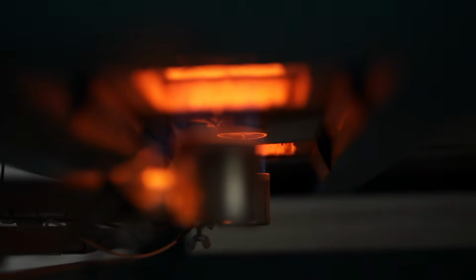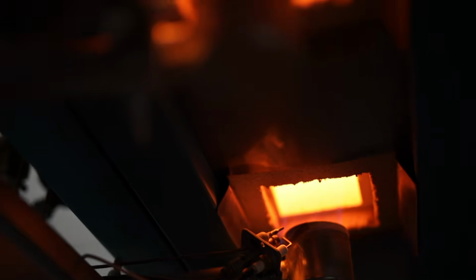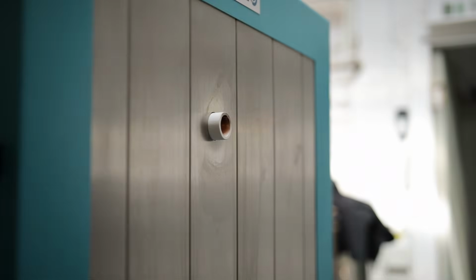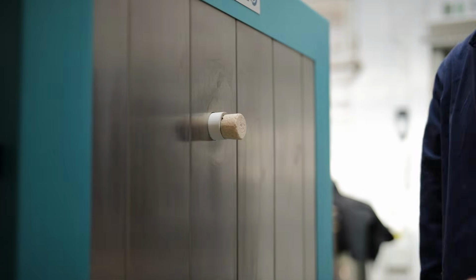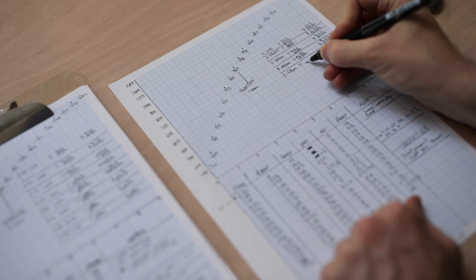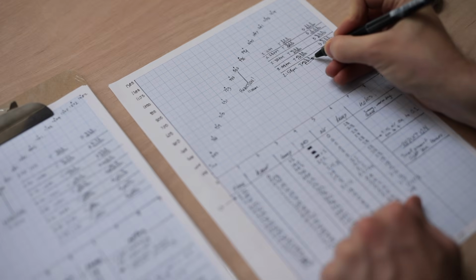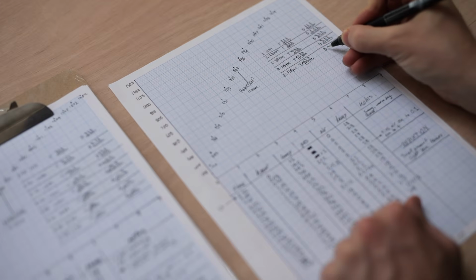As the firing reaches its crescendo, I pay much more attention to it, checking the cones consistently and ceasing any other task I was doing, as throughout the day, as the kiln plods along, I can be doing other things, but every half hour on the dot, my attention comes back to the kiln and I assess what's going on, and I check the cones through the spy holes far more regularly, as I need to be very accurate regarding the time I end the firing, as if I underfire a little bit and the pots are too cool, they'll look dull and matte, and if I overfire the pots, I risk the glazes flowing off the vessels and ruining the kiln shelves.